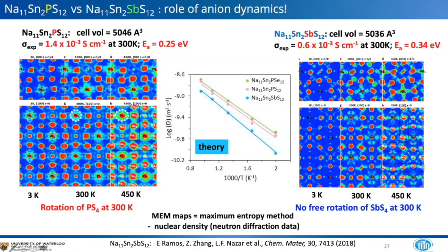And you can see that at 3 Kelvin, there is even disorder obtained in that PS4 group, whereas at 300 K, that is rapidly rotationally disordered. And this is also true, of course, at 450 K. So we see this rotation at 300, whereas in the antimony analog, there is no motion whatsoever at 3 Kelvin, whereas at 300 K, there is only some disorder, but not actual rotation. So this provides a real contrast between these materials, which we wanted to look into in greater detail, and that's shown on the next slide.